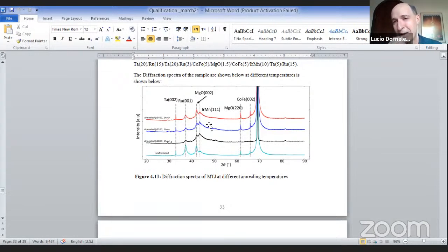If you isolate the width in the Scherrer equation, you see that as you go to higher angles, the width has to increase. The same thing may be valid for the one that you say is cobalt iron 002. The width is very small, so I don't think they are from your sample. Most peaks should be wide because the films are thin. But anyway, this is not MgO, I can assure you. I did some calculation, and it should be at least 10% wider.